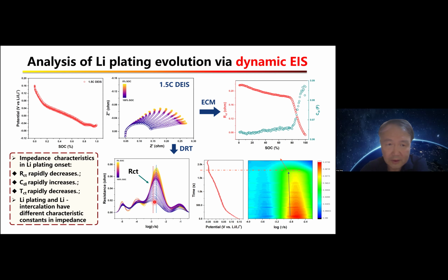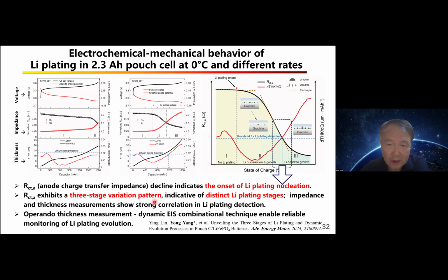Using a 2.3 ampere hour pouch cell as a model system, if we charge the cell at 0.2C and 0.5C, we can see that at the higher rate, lithium plating shows an earlier onset. Interestingly, if the lithium plating is less, we can use EIS to follow the full process. But if the amount of lithium plating is large enough, at the middle or end of charging, the charge transfer doesn't change linearly with the charge we used.